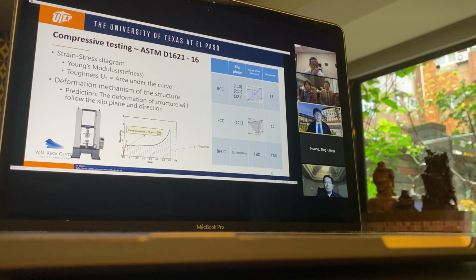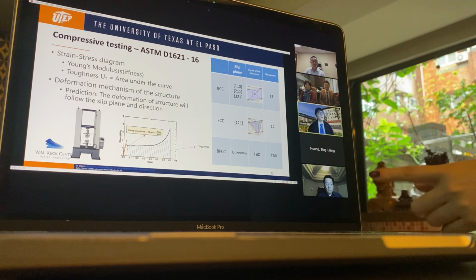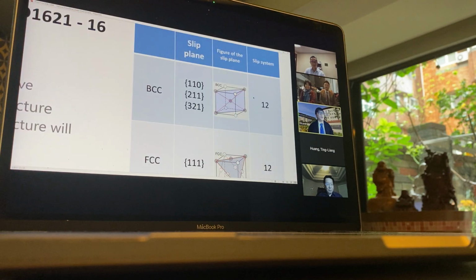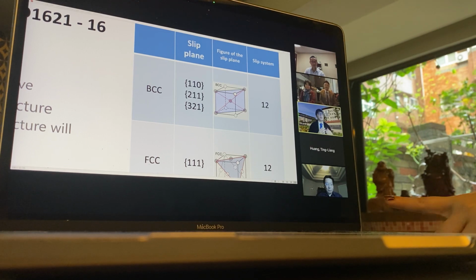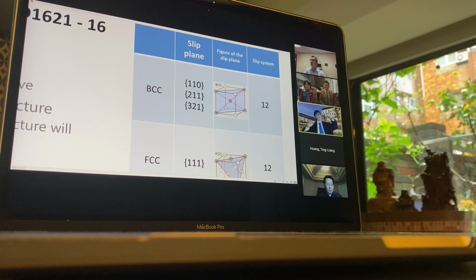As I mentioned earlier, the anticipated deformation will follow the slip plane. More specifically, BCC will follow the 110, 211 and 321 planes, and the 111 plane for FCC cubic. From the first picture here, we can see the BCC slip plane is just like that, following a diagonal line.